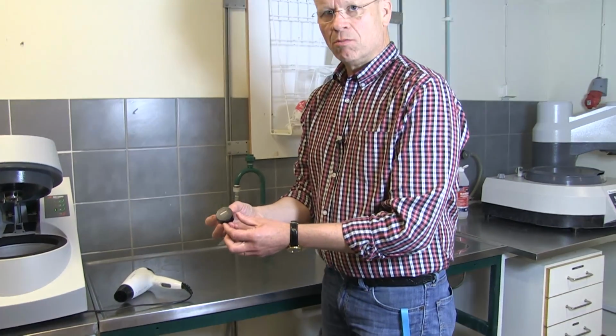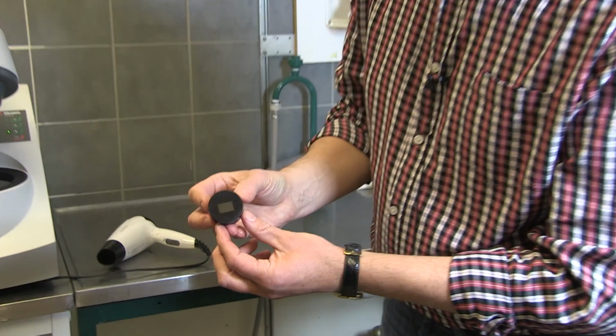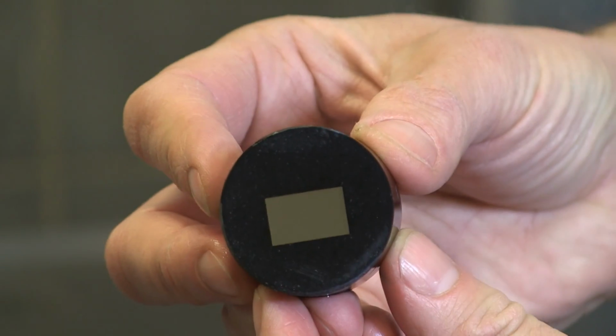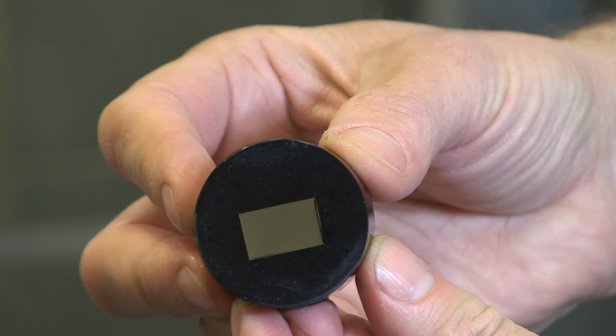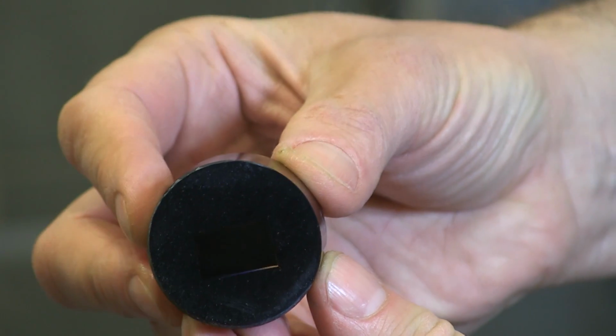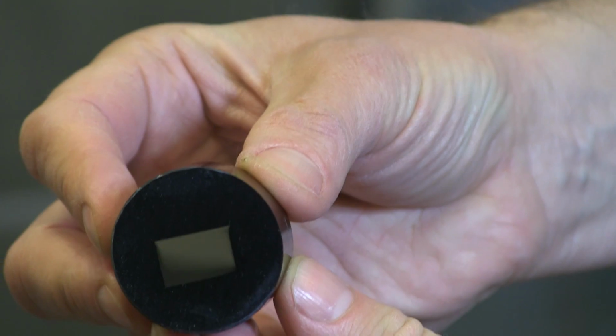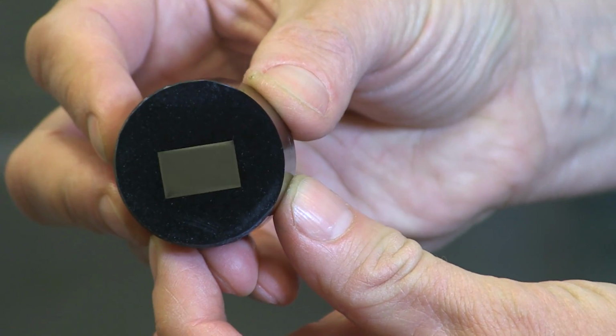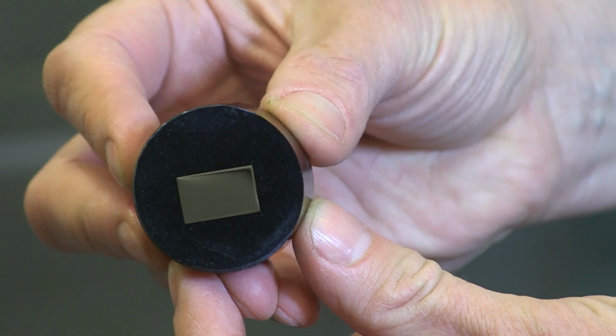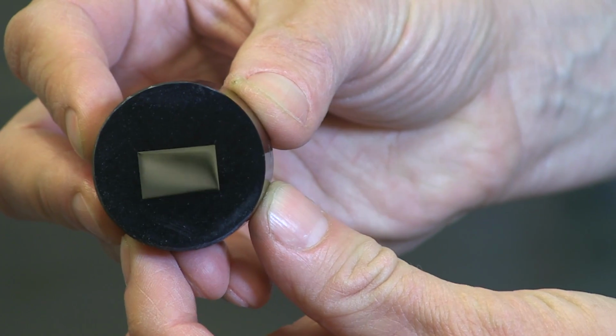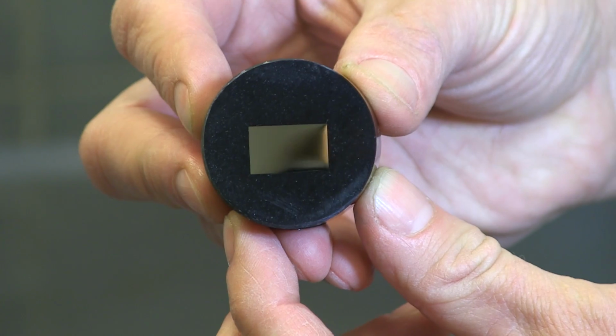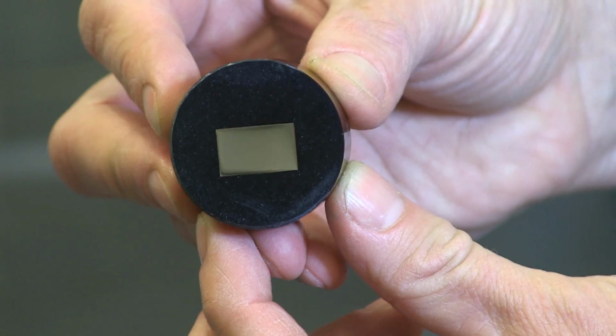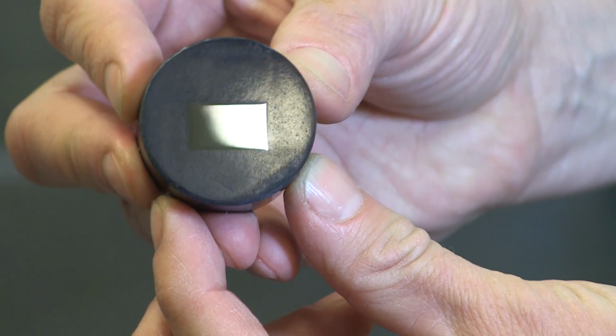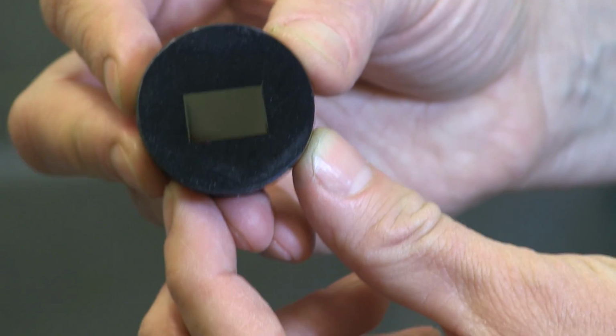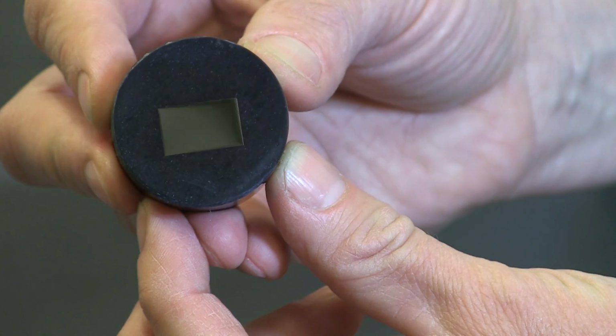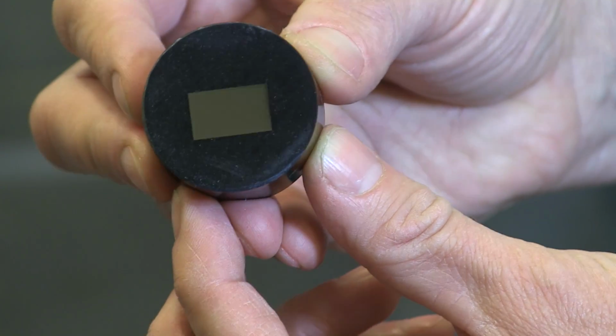So now if we zoom in on the sample, in the best case you can see a mirror-like surface. This is how it should look. I move it around a little bit, so with the reflections maybe you can observe it somehow. And if it's full of scratches, maybe you did one of the steps too fast, or maybe there was some dirt on some cloth, but as I've said before, if you clean the sample between every step, it will be very rare to find big particles on the wrong disc.